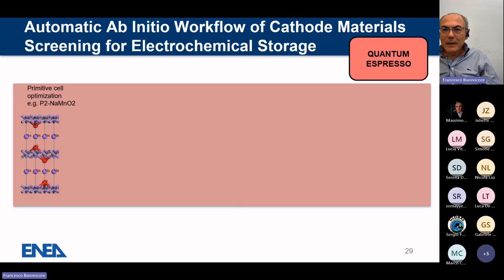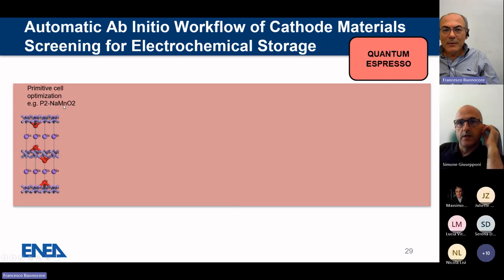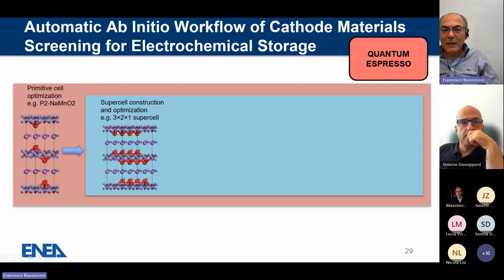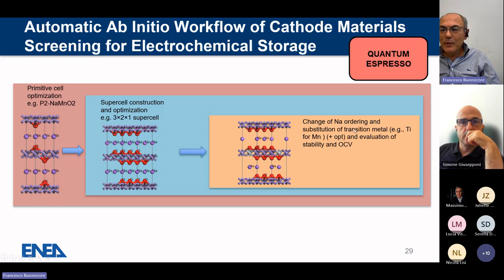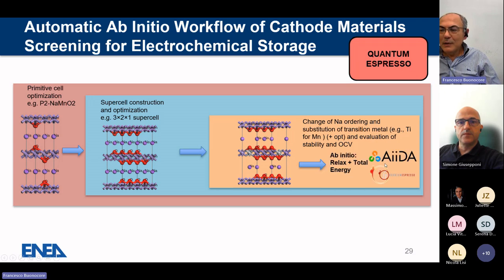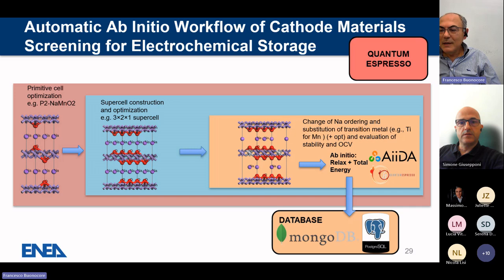And in the typical workflow, we start from a primitive cell, for example, manganese oxide with sodium atoms intercalated. We build a supercell and we optimize this supercell, and we do all the possible substitutions in a random way to evaluate the formation energy and the intercalation potentials by using AiiDA and Quantum ESPRESSO. For every structure, we perform a relax calculation. We hold this data within the MongoDB database.